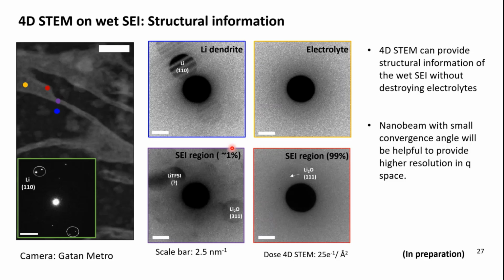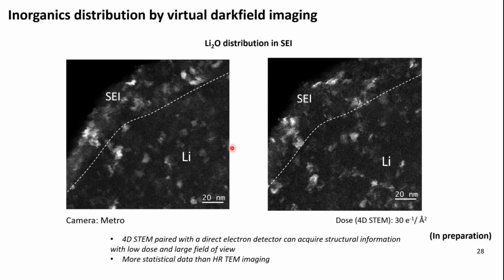And because of this, I believe we need to use nanobeam with a smaller convergence angle to increase resolution in Q space, such that we can see some bonding information at low Q space. Otherwise, we have too many amorphous structures, so we cannot resolve such information for now. What's really impressive with the direct electron detector is that we can acquire the inorganic distributions in SEI with low dose rates. So what we can do is locate the inorganic compounds distribution in the SEI by virtual dark field imaging from 4D STEM data sets.